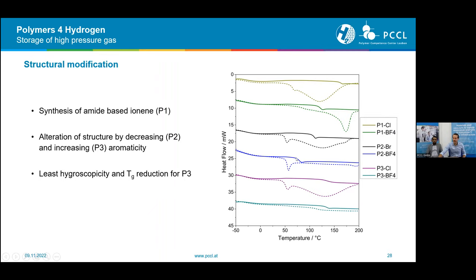As you probably know, polyamide is somewhat susceptible to water uptake. However, from those results, we could see that, as expected, if you decrease the aromatic content, also the TG decreases. So for polymer 2 here in blue. And the increase in aromatic content, interestingly, did not increase the TG before the anion exchange, but it increased the TG after the anion exchange. And here you can see there's almost no difference between those two. However, before the anion exchange, the polymer is completely water soluble, and afterwards it is not soluble in water anymore.